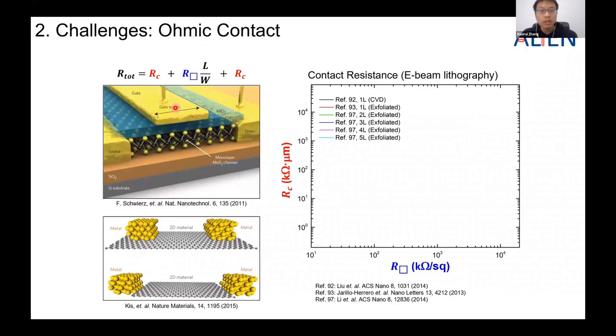So we all know the transistor has a large contact resistance between the 3D metal and the 2D materials. The reason is there's a Schottky barrier between the 3D metal and the 2D materials. If we do a little review and we plot the contact resistance as a dependence of the material quality or material sheet resistance, we can realize that for monolayer 2D materials, in order to reduce the contact resistance, the way is to have a better, more conductive material, or in other words, to reduce the sheet resistance of the material.